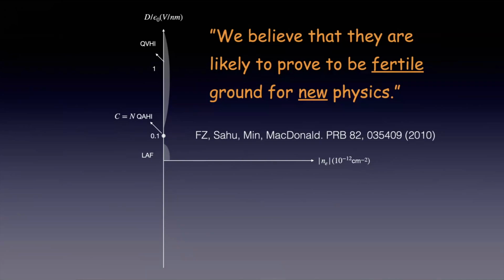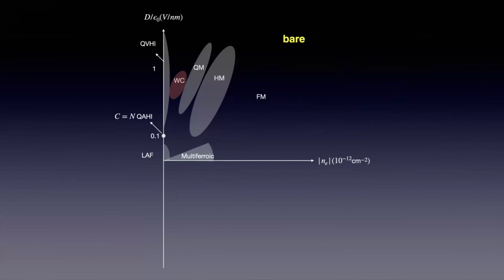Now let's take a look at how that's verified by experiments nowadays. If we start from the high density and go to lower densities, we'll see this four-isospin, long-range interacting metal become kind of Stoner magnets. So the spin-valley has four flavors, right? Not all of them will appear at the Fermi energy. So we'll have this half metal, with two isospin flavors appearing at the Fermi energy. If you lower the density, you get one appearing at the Fermi energy. Of course, if you further lower the density, there is kind of a Wigner crystal regime, right here. And what's interesting is superconductivity also appears in this system.